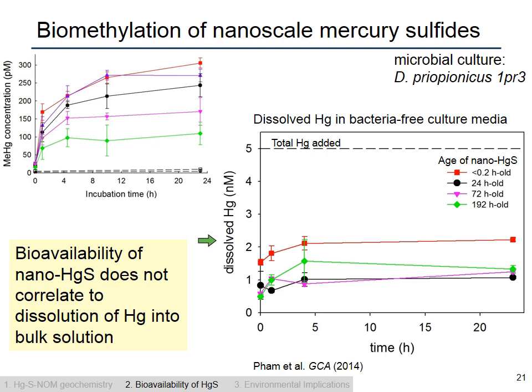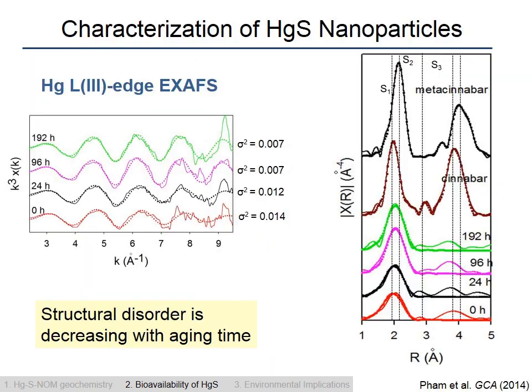So the take home here is that the bioavailability of the different forms of nanoscale mercury doesn't correlate with the dissolution of mercury into bulk solution. But we did see that it seemed to correlate with the actual structural characteristics of the nanoscale mercury. So this is extended X-ray absorption fine structure spectroscopy data, where we're using this method to look at the local coordination environment of mercury in these mercury sulfide nanoparticles.